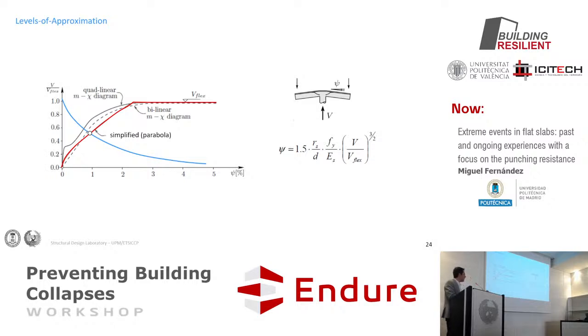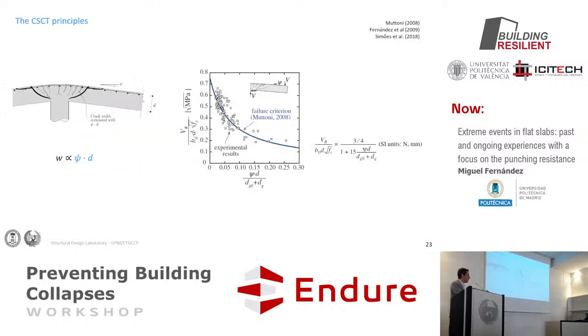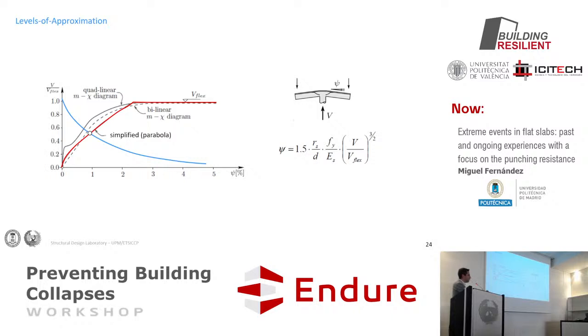And then you may calculate this demand that we are having in the critical shear region by a simplified assumption. For instance, we take a simplified parabola like this one. Well, it is derived on some configuration, with several simplifications, but in fact, it is a right proposal. This is very simple. So you have the failure criterion defined by this simple equation and the load-rotation demand defined by this equation. This is what you find for design, at least in the Swiss code and also in the Model Code for lower levels of approximation. So this is what you can do in a very simple manner.